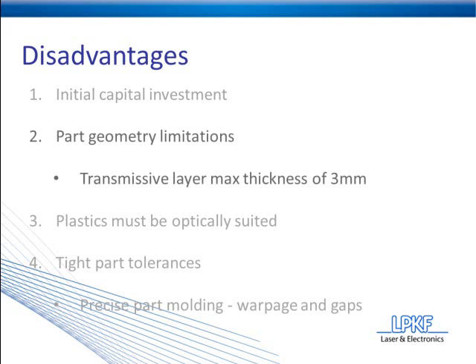Disadvantage number 2 is part geometry limitations. Now, every joining method is going to have their own limitations. Laser plastic welding has a few, and the most obvious is the transmissive layer thickness. We recommend a transmissive layer thickness of no more than 3 millimeters. And the reason why is because anything thicker than that, and you're going to have a tough time transmitting enough laser energy to the weld interface to create the adequate heat for a quality melt. Now, there are a couple other part geometry limitations. They're a little more advanced, so we're not going to cover them here. If you'd like more information on those, again, you can get them from the design guidelines document that I will be introducing to you here in a minute.